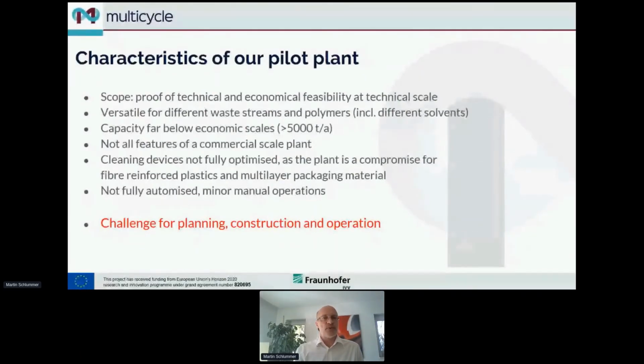And of course, such a small scale pilot does not contain all features of a commercial scale plant. For example, the cleaning devices are not fully optimized, since they had to provide a compromise for fiber reinforced plastics, glass fibers and carbon fibers on the one hand, and residues from end-of-life multi-layer packaging on the other. Here we have residual foodstuffs and whatever in there, which is a different cleaning task. And of course, it is not fully automated, and we still had some manual operations, but very minor. To be honest, it was very challenging for planning, construction, and finally also in operation.